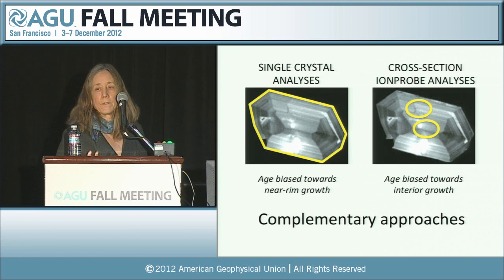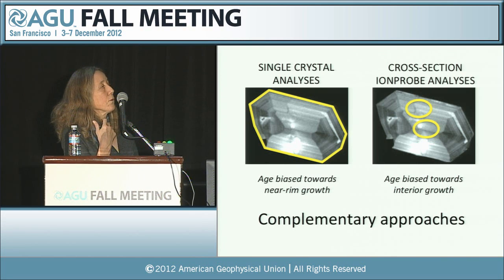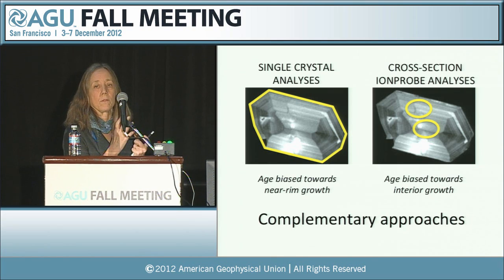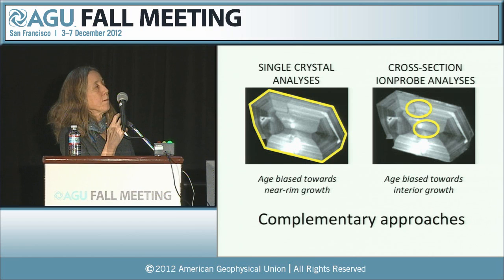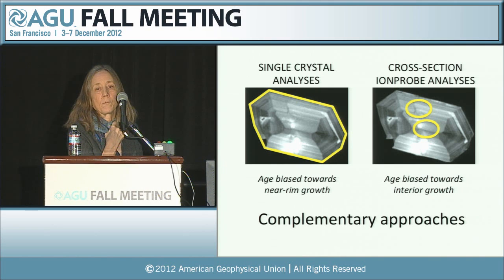They're giving us different insights into the system. So the single crystal analyses are really biased towards the near rim growth because that's volumetrically where most of the zircon is. On the other hand, when we go in and we expose a cross-section and do spot analyses, we're going to be biased towards the interior growth. It's very difficult to get a true rim analysis because you can't really get the spot on the rim using these approaches.